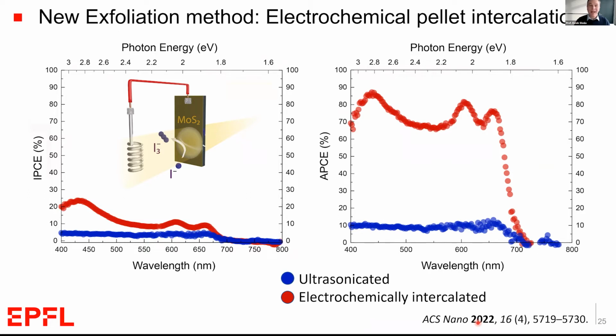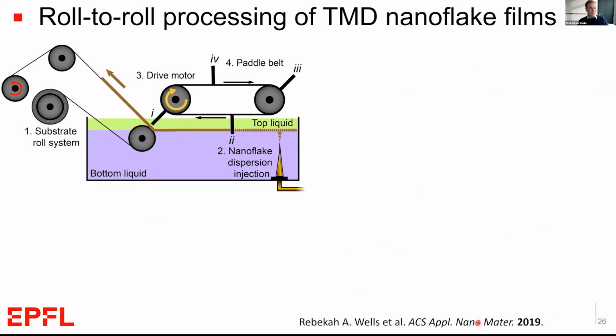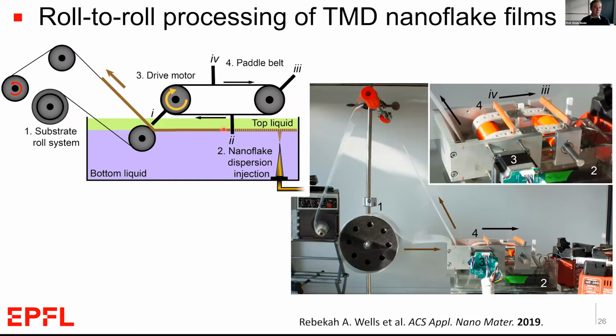But nevertheless, coming from a chemical engineering background, I really want to convince myself that we could do this on a scalable, global scale. So in fact, we did this recently just to show that this liquid-based self-assembly method, which is needed to make these films in good contact with the substrate, can be used on a roll-to-roll type device.